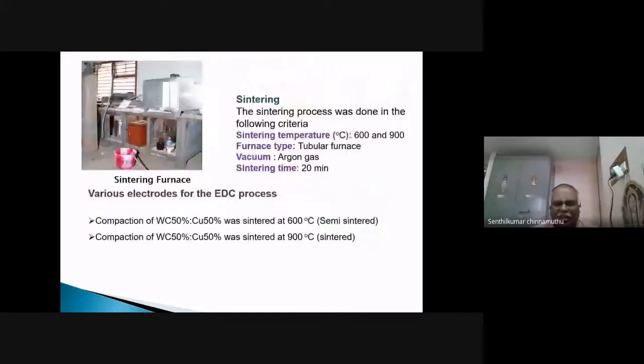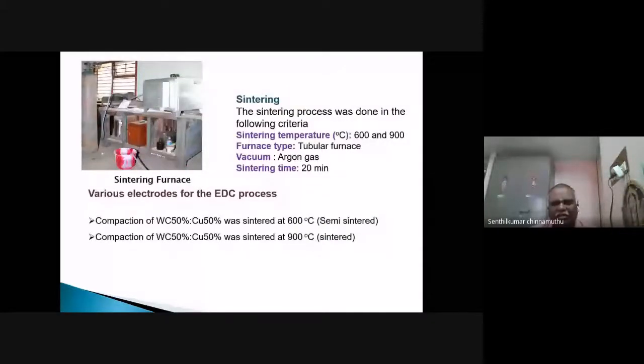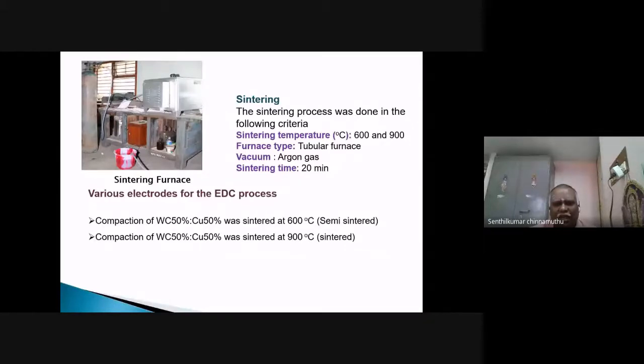Then sintering is carried out in the tubular furnace with an argon atmosphere, and the sintering time is 20 minutes. Why do we have to use argon gas? Without argon gas, the atmospheric air is inside the furnace, which contaminates the green compact. Whereas if you use argon gas, it evacuates the atmospheric air, and the environment becomes inert, so that we can obtain a proper sintered and semi-sintered product.